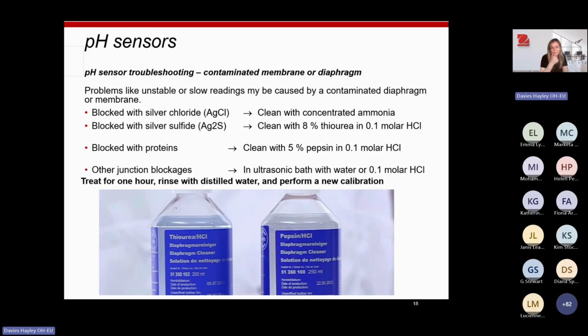If your electrode is blocked with silver chloride, for instance, you can use concentrated ammonia to give it a clean. Give it a wipe with the concentrated ammonia, and then afterwards rinse with distilled water as well. If your probes are blocked with silver sulfide, you can clean with an 8% thiourea in a 0.1 molar HCl solution.